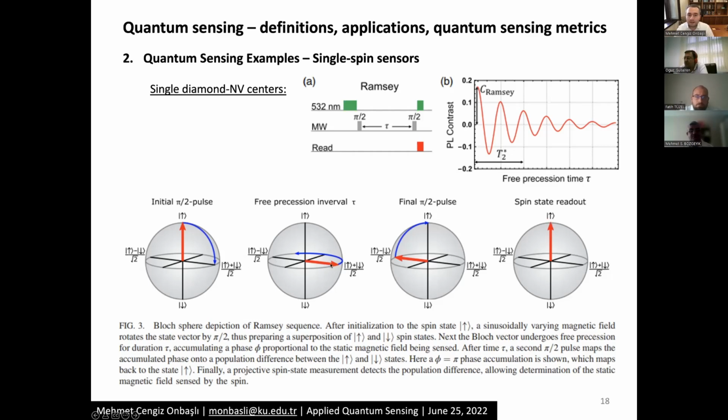During this relaxation period, we apply the external magnetic field that we want to read. As a result, we get these Ramsey sequences as we are doing the readout. So what we do to get these plots is we vary the tau and repeat this whole experiment for different tau values.